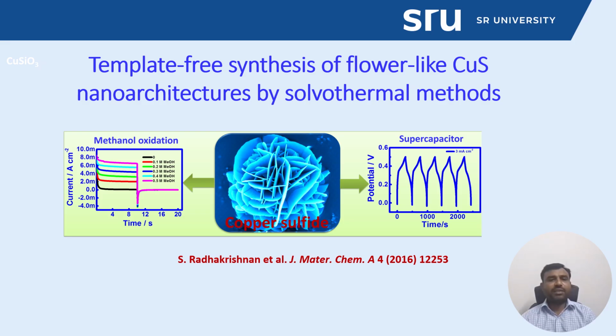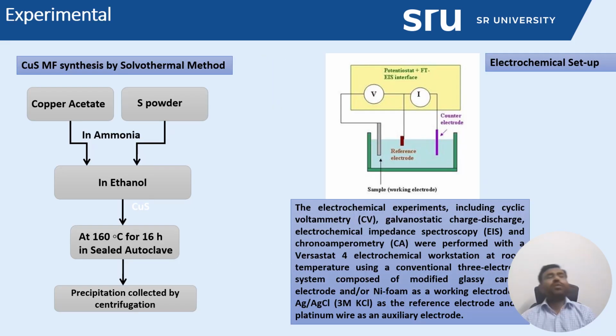Compared to the previous synthesis, here the synthesis is slightly changed. I will explain in the following slide. In the previous slide, we used SiO2 as a hard template to prepare the hollow structure. Here, we did not use any template method. We just took copper acetate as the copper precursor and sulfur powder as the sulfur precursor, and mixed them in ethanol as solvent. In the previous reaction we used water as the solvent, but here we used ethanol.